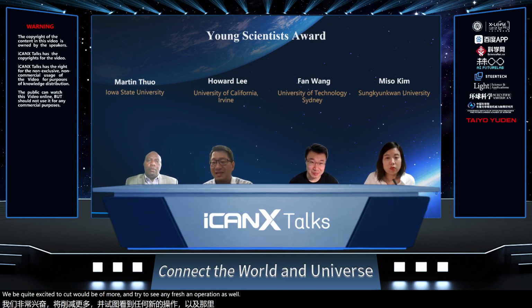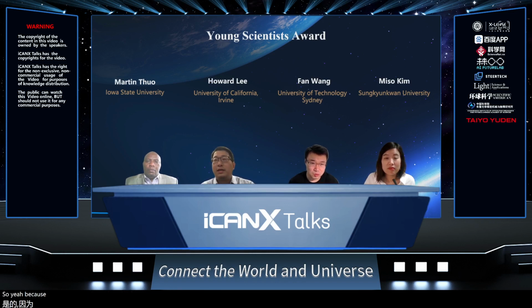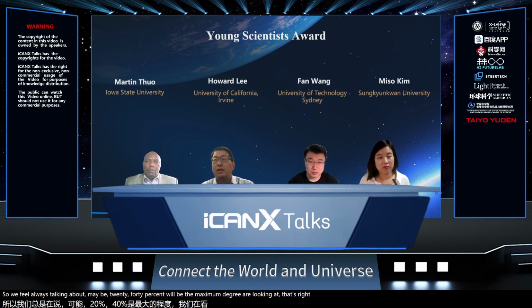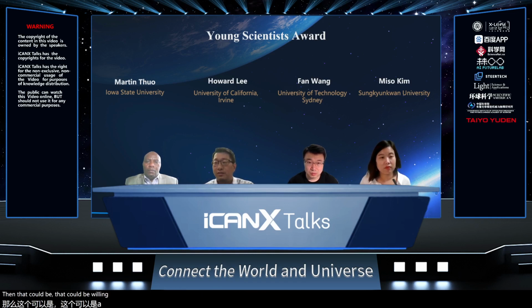We'd be quite excited to talk with you more and see about any collaboration. Maybe we can build some collaboration. One final question: for the fiber one, if you make the layer really thin, let's say 50 nanometers, what's the loss of the light? What's the efficiency? For metallic structures, we are always talking about maybe 20-30% at maximum. That's right. But if we use a dielectric structure, with a really low-loss metasurface, then it could have really high efficiency, 90% or even higher. But the dielectric structure is more difficult to fabricate than the metallic structure.